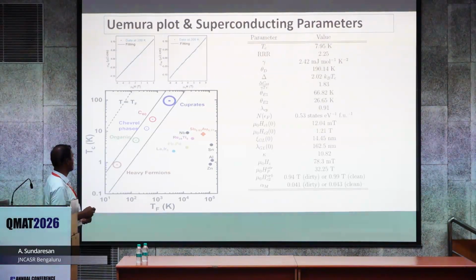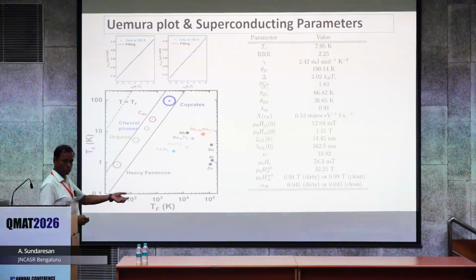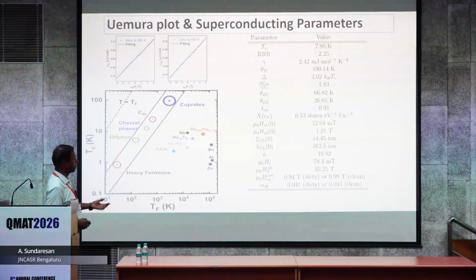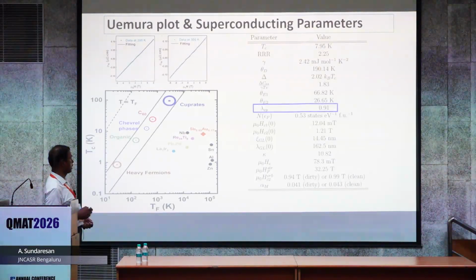In the Uemura plot, our material does not fall onto the simple metallic system, it's close to the alloy, again indicating possible strong coupling superconductivity in this system.